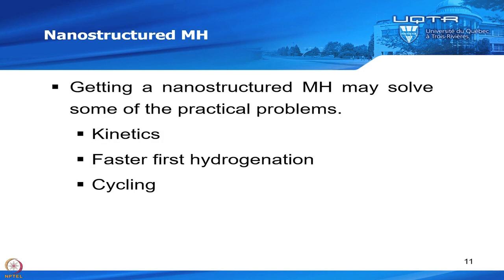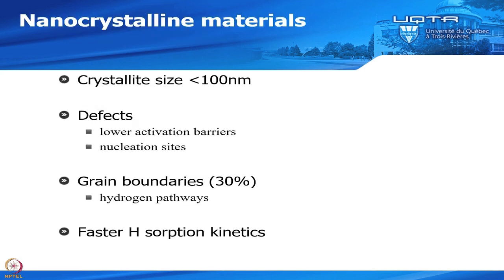So, nanostructured metal hydride. Getting a nanostructured metal hydride could solve some of the practical problems, for example, the kinetics or the first hydrogenation. So we could make the first hydrogenation much faster, and you could make the alloy much easier to cycle. So after many cycles of hydrogenation and dehydrogenation, you will not lose so much capacity. So what is the definition of a nanocrystalline material? Well, the classical definition is that your crystallite size should be less than 100 nanometers. The crystallite size is the coherent domain of your crystal, okay?